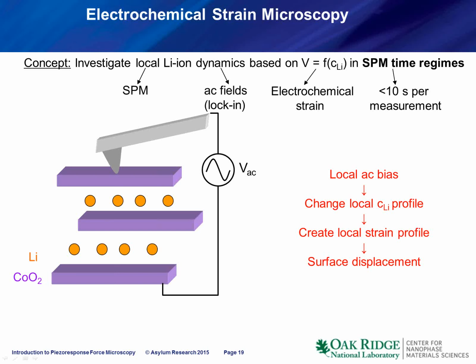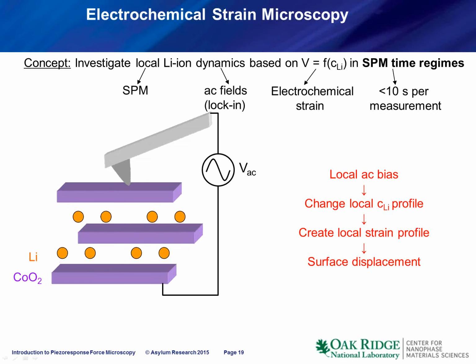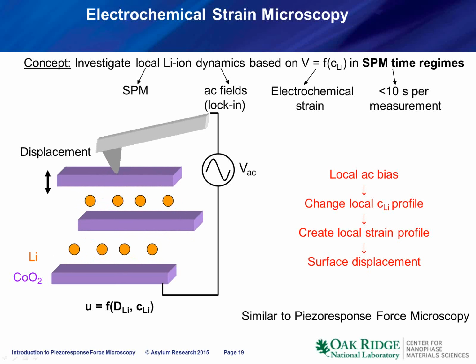How significant is this effect? In fact, it is pretty significant. In lithium cobaltate, which is the material that is used in the cathodes of batteries in your cell phones and laptops, the expansion of the lattice on lithiation is about 40 picometers. The SPM in the band excitation or DART mode can easily measure several picometers. So it turns out that by measuring surface expansion and contraction, we can study electrochemical reactions in a single unit cell over a lateral domain of the order of 10 nanometers. Compared to macroscopic current-based electrochemical measurements, this increases the sensitivity by a factor of a million to a billion. And so this is the illustration of how the ESM works.